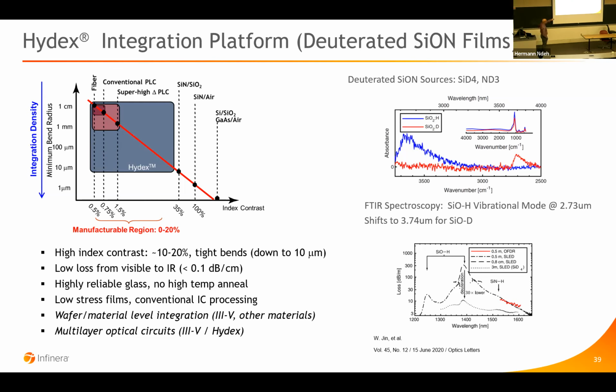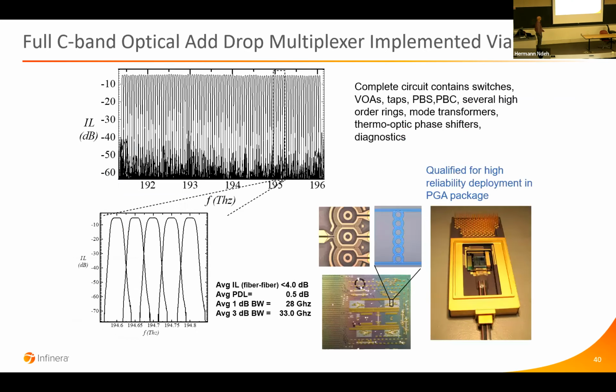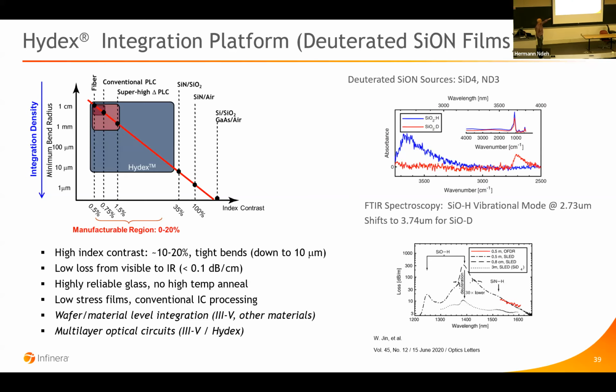In this case, this is work that shows a 30x reduction. It's actually over 100x when you work to really get all the kinks out and make it in devices. So you go from dB per centimeter losses to dB per meter losses in your waveguides. What's also important is there are other ways you can get the hydrogen out of your film. One way people commonly do it in silicon nitride is they just heat the film up to 950 degrees C and anneal it for 8 hours to get all the hydrogen out. The problem is compound semiconductors, III-Vs, don't like to be annealed at 950 degrees C for 8 to 10 hours. So silicon nitride with that kind of low hydrogen content hasn't been readily integratable into the devices.